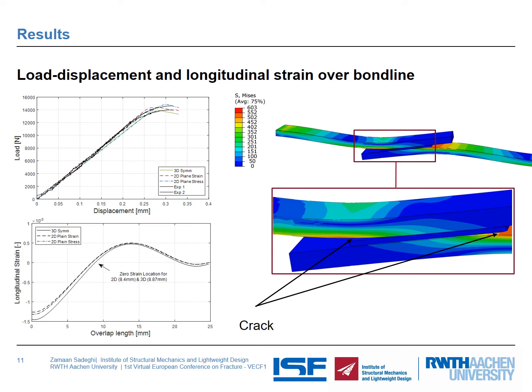Since we had to mount the strain gauges at the location of the zero strain point, the longitudinal strain over the overlap length was also determined. As you can see, overall between the 2D and 3D models, the longitudinal strain shows more or less the same values, but for the 3D model, the curve is somewhat shifted towards the right, and the location is a bit different, which was expected because the strain in the width direction is not expected to be constant for the single lap joint.